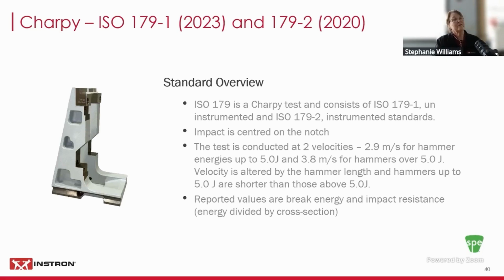Another difference is in sample size. ISO 179, the sample is, I believe, 80 millimeters long, 10 millimeters deep, and they have a set preferred thickness of 4 millimeters. So to be in full compliance with the ISO standard, your sample is going to be shorter, it's going to be deeper, and it's going to have a defined thickness to it.